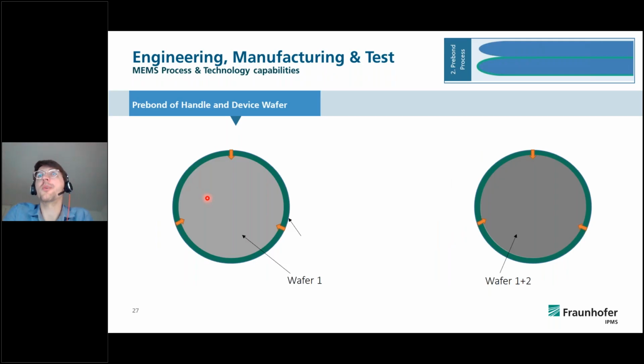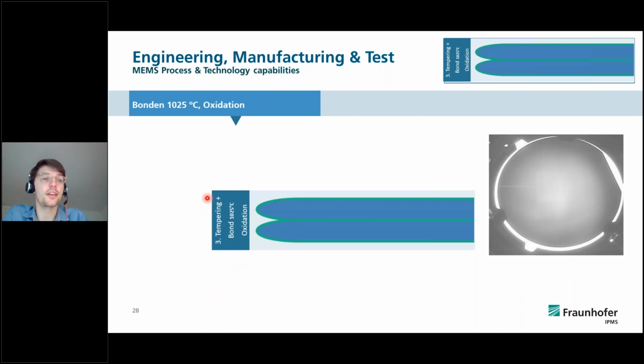Later on, when we try to bond those wafers together, we actually have a pre-bond process which works with pressure. So you pressure those wafers together so that they have a basic bonding done, which is not sufficient for processing, but getting them later on into the furnace to get an oxidation done to bond them basically together. It is sufficient, and then we get really the entire bonding of those two wafers, which you cannot break or open up again.